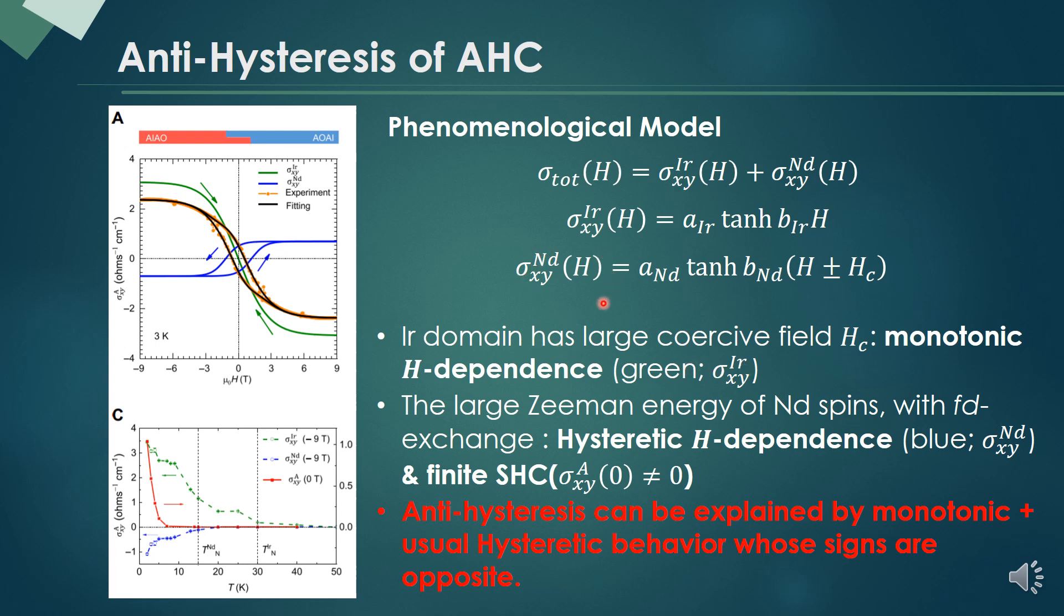For the neodymium spin ordering contribution, it has a large Zeeman energy. Therefore, it can induce some domain switching. So we adopt the hysteretic H-dependence with a finite spontaneous Hall conductivity in here, the blue line.